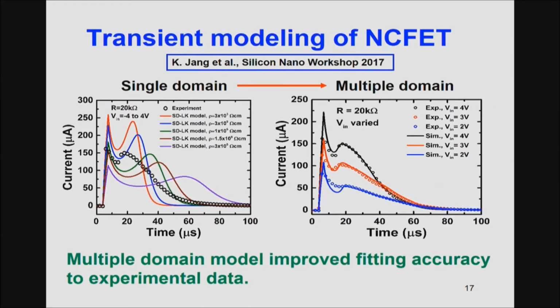But the one thing I wasn't really satisfied with in my model is the fitting accuracy. So far, my model is based on a single domain model. This graph shows one example of the transient current response to a step input. The model fitting accuracy wasn't really great. But now we introduced a multiple domain model, which improves the fitting accuracy very well. So now I'm rebuilding my NCFET model with multiple domains.